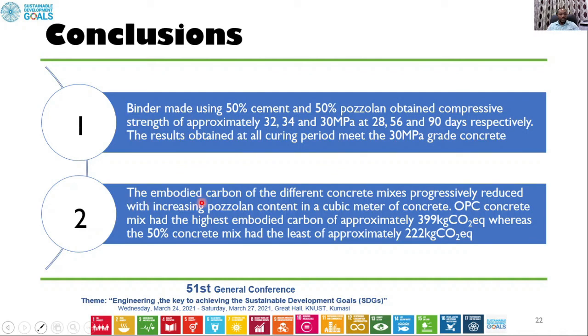Number two, the embodied carbon of different concrete mixes progressively reduced with increasing pozzolan content in a cubic meter of concrete. The OPC had an embodied carbon of 399, whereas that of the 50% concrete mix, which was the lowest among the concrete mixes, was 222 kilogram carbon equivalent.